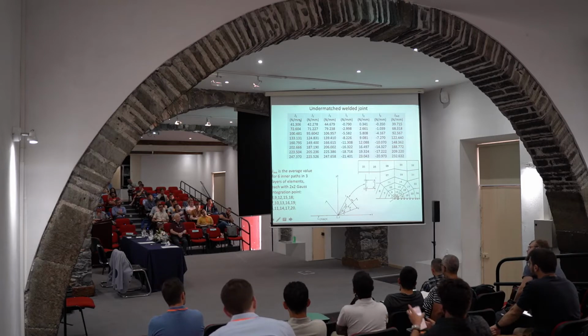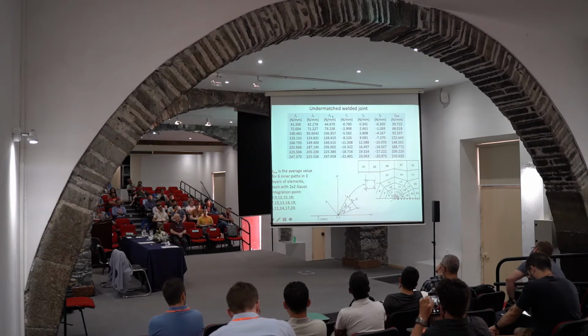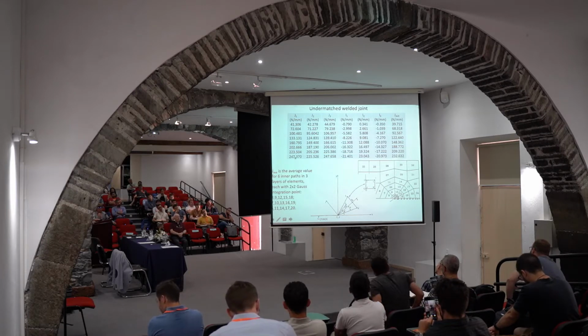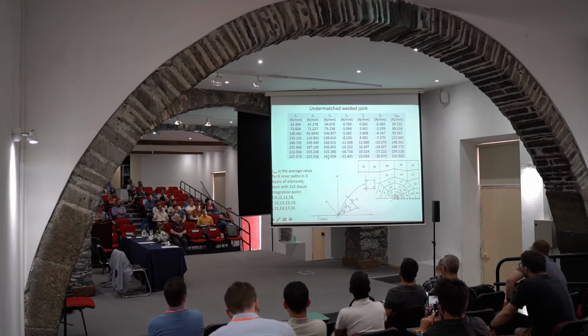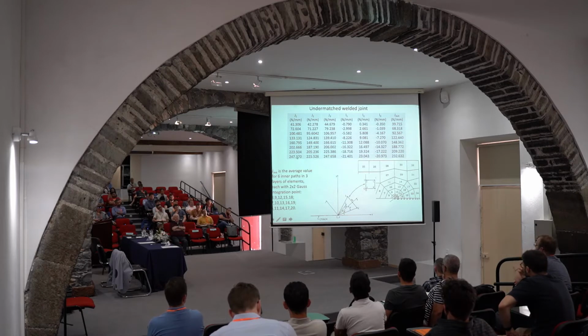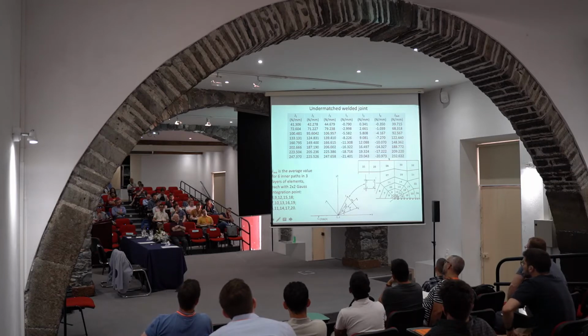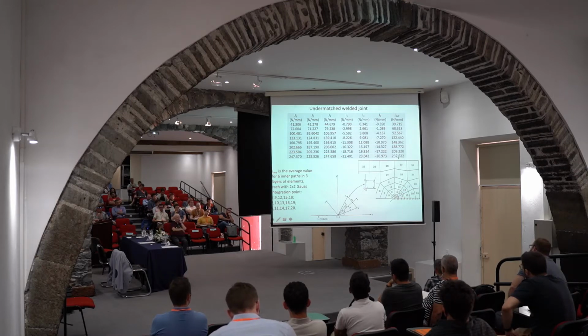And here you can see now J integral along paths 1, 2, and 3, which cross over interfaces, so their values are a bit different. For example, in this row you can see 247, 225, and then once again 247. These 2 are really almost the same, but that's coincidental. We should focus on this difference, which is about 10%. But then if we combine these integrals with line integrals, as we should, as I showed a couple of slides ago, then we should get something close to this average value, which is based on those paths which are inside the weld metal.